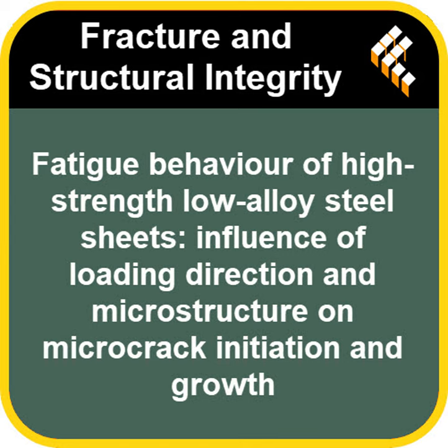This is really intricate stuff. It leads us to something called the cyclic stress strain curve and this term N prime, the cyclic strain hardening exponent. You said the study found something deeper here. Yes, this is where it gets really fascinating. They found what they called double N prime behavior, but only in the TD and DD samples. Double N prime. What does that mean? Okay, so the RD samples showed a pretty consistent hardening behavior across different strain levels, one N prime value. But for TD and DD, the way they hardened seemed to happen in two distinct stages. If you plotted their stress response at midlife, the curve had two different slopes.